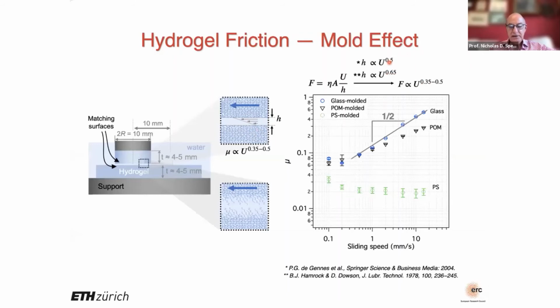But in the case of the dangling chains, because we're getting no speed dependence, we believe that what's happening as we go faster and faster is that the moving part of the fluid extends further and further down into these dangling chains, and it compensates and gives you no speed dependence.